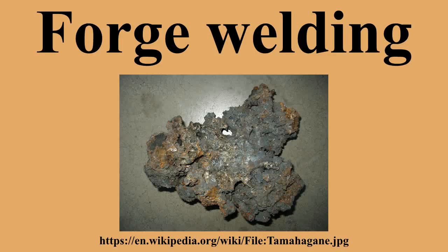Temperature. The temperature required to forge weld is typically 50 to 90% of the melting temperature. Iron can be welded when it surpasses the critical temperature where its allotrope changes from alpha iron to gamma iron. Since the critical temperatures are affected by alloying agents like carbon, steel welds at a lower temperature range than iron. As the carbon content in the steel increases, the welding temperature range decreases in a linear fashion. Iron, different steels, and even cast iron can be welded to each other, provided that their carbon content is close enough that the welding ranges overlap.